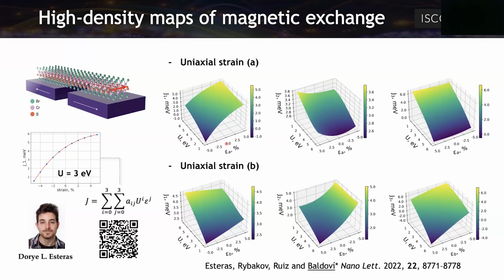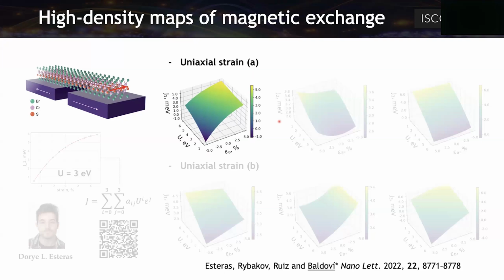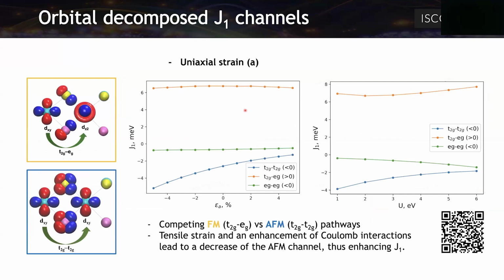with strain. We can observe here that when we are keeping, for example, a particular Hubbard U, we are now performing a strain, and when we expand the material along this direction, the J1 is increasing. And this is direct because we are applying strain along the A direction, and J1, as I said before, is contained in this direction.